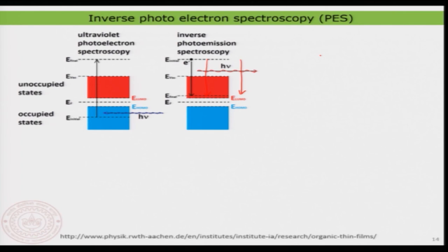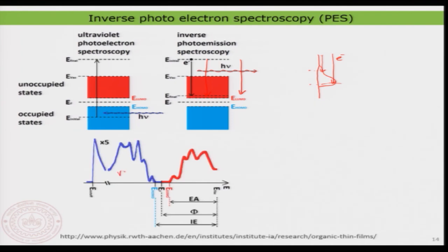Just to have an understanding, let us see, I have here a density of states of the unfilled levels, which looks like this. When I am injecting an electron into this particular energy, you see clearly that the density is lower, and if you are injecting an electron into this particular energy, you see clearly that the density is higher. So, that means the amount of photons emitted by the material will also depend on the density of states to which the electrons are injected. Therefore, you can see the valence band and the conduction band if you combine both ultraviolet photoelectron spectroscopy and inverse photoelectron spectroscopy together. So, that is the strength of this technique.